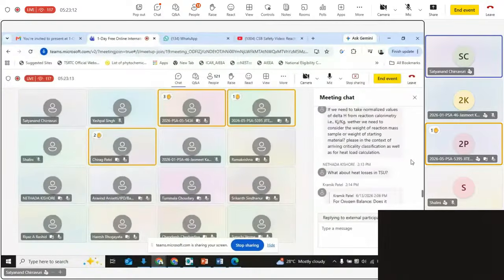First of all, I'll ask Nethaja Kishore. Heat losses in TSU are there. TSU is not an adiabatic system. That's why, as a screening tool, it will tell you at what temperature you suddenly see a sudden temperature rise or a pressure rise, indicating that there's a decomposition. Once you have a feel of at what temperature there is going to be a pressure increase or a potential onset, that is the information which you can use further to design your process. It is a pretty good tool, because you will be able to understand exactly where the onset is happening, and also what kind of pressure rise will happen, how much pressure and how much temperature. But it is not an adiabatic system, so obviously you will have heat losses.